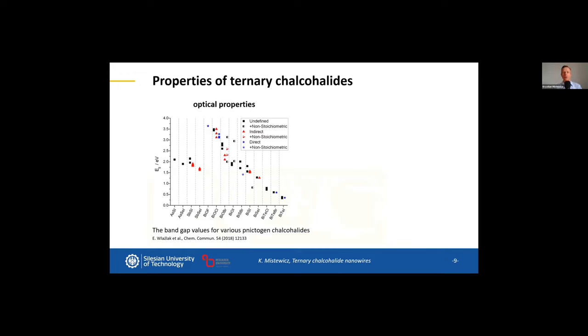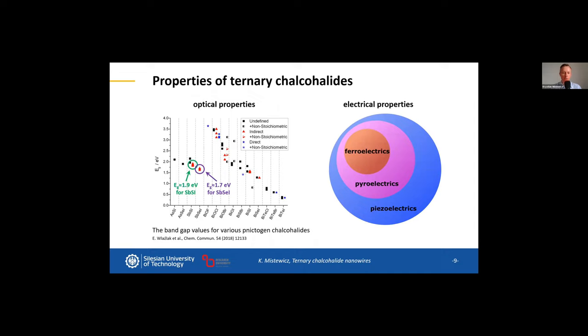The optical band gap of ternary chalcogenide halides spans a very wide range of values. However, for these two specific materials the energy band gaps are about 1.9 and 1.7 electron volts for antimony sulfoiodide and antimony selenoiodide, meaning these materials possess narrow band gaps beneficial for optoelectronics applications. The electrical properties are also interesting because the majority of these materials are ferroelectrics, which means they also possess pyroelectric and piezoelectric properties.